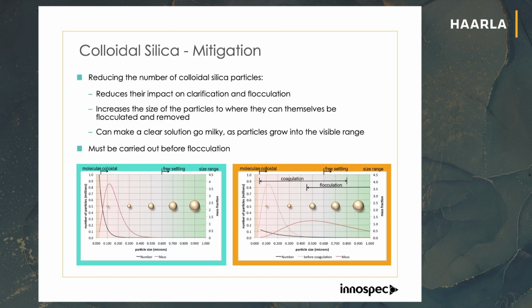So what you need to do here is increase the size of the silica particle, the colloidal silica. By increasing that size, it moves from something that will not settle to something that will settle. So that removes your problem in the process. It's very, very important to do that, and we normally do that by a process called coagulation. In coagulation, you're increasing the particle size. Then you flocculate that particle, which is then very easy, sorry, to filter, and therefore removed from the process.